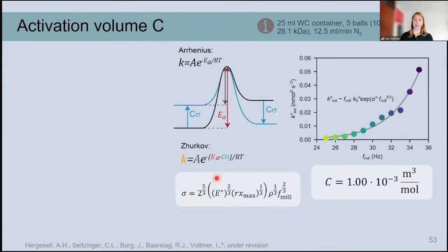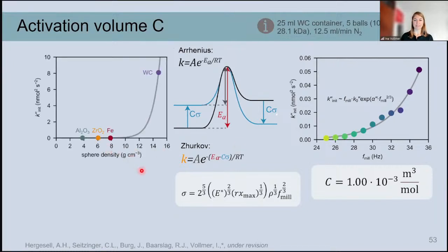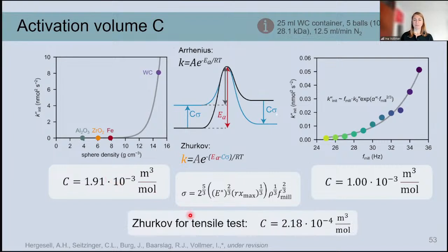And so we also applied this fitting to the experiments with the different densities. And we also get a C value here. And as you can see, they are actually surprisingly close, although not the same, for changing the frequency and changing the density. And when we look at the papers of Zhurkov that this model is taken from, then he obtained, of course, quite a different value for C, which is an order of magnitude lower. But this is also because he actually used tensile testing, where this can also be expected to be quite different.